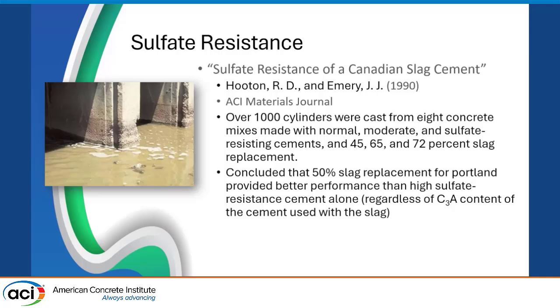Then we get into some of the durability aspects of slag cement. For instance, sulfate resistance. Doug had a paper called Sulfate Resistance of a Canadian Slag Cement. This is one of the references in ACI 233, and it was published in the ACI Materials Journal. Here they did over 1,000 cylinders cast from 8 concrete mixes, looked at 45, 65, and 72% slag, and basically concluded that 50% slag replacement for Portland generally can provide better performance than a high sulfate resistant cement, regardless of C3A content. So you could use a Type 1 cement with 50% slag and get better performance.